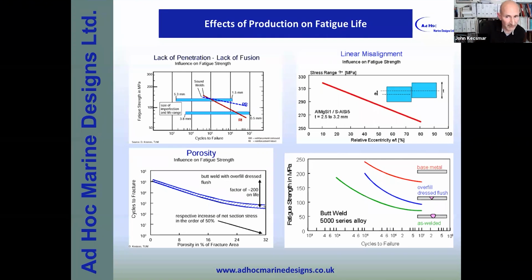Similarly, with misalignment, just a simple 10% misalignment of plates can result in adding 30% to your stress concentration factor. Similarly, if there's a mere 1 degree angular misalignment, that also adds another 30%. If you have the two together, that's actually 60%. So suddenly that weld is no longer performing as you had designed it. It's actually experiencing stresses of 1.6 times that of what you've designed it for.